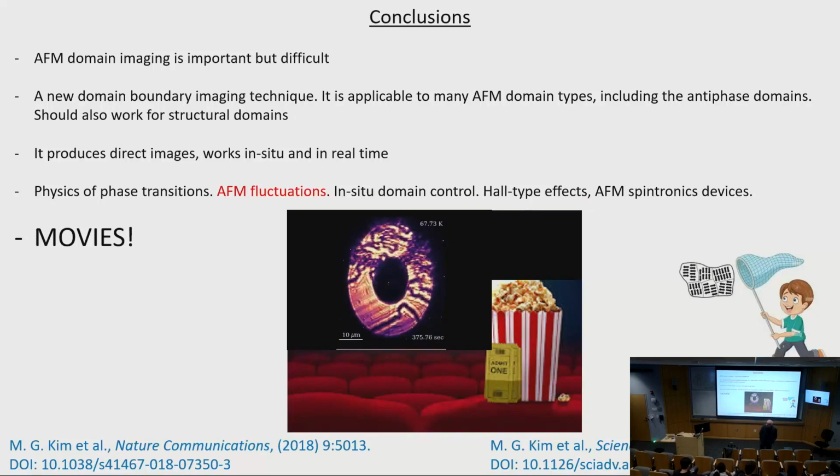Yeah. In fact, as we get closer to the Néel transition, the domains will become very small. They will become nanoscale. Instead of this image, you will see the speckle pattern. We see it, right? Across the transition, I would expect the same. At the critical transition, opalescence, right? From nanoscale size domains, you get the speckle pattern. Okay. Well, it is fluctuating, right? Right. But we cannot measure fluctuations that are faster than 0.01 second, whatever, right? Yeah. So this is what we measure. Maybe there are a lot of faster fluctuations very close to the Néel temperature, we cannot tell.